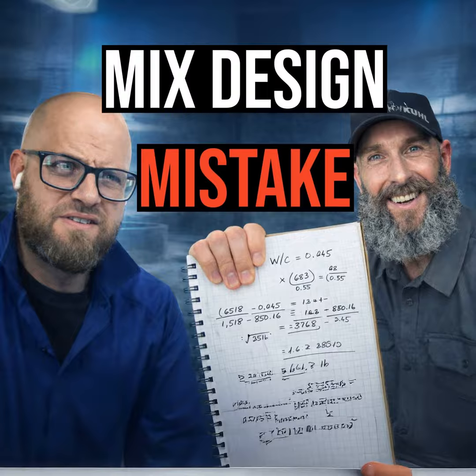Okay, so right now with our mid-range water reducer, you're at 4 ounces per hundredweight, which is a lower dosage, but it's a standard dosage. If we doubled that dosage to 8 ounces per hundredweight, now we're up to 44 fluid ounces per cubic yard, which, if you can't tell by my voice, that's a lot to me. But I'll put it in other terms: that's a third of a gallon for 1 cubic yard. Does that sound like enough admixture for you per cubic yard? Sounds like a lot. Now, you never sell just one cubic yard; normally you sell 5 or let's say 10 cubic yards. So you times that by 10, and now that's 3.4 gallons just for that one admixture. But normally they have them in bottles with fluid ounces, and you can look down and see them, and that comes up to 440 ounces per 10 cubic yards.